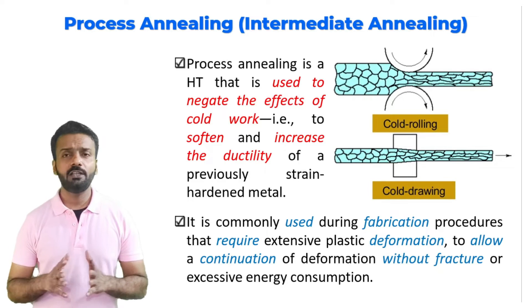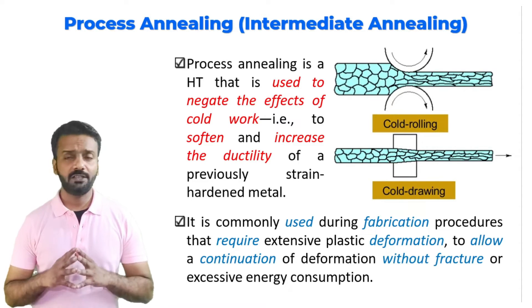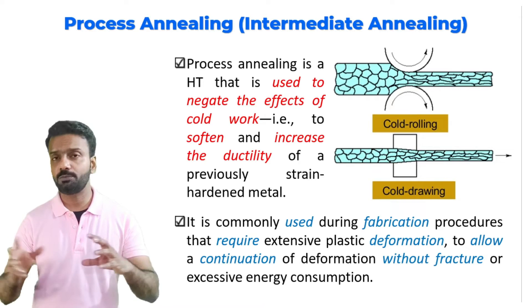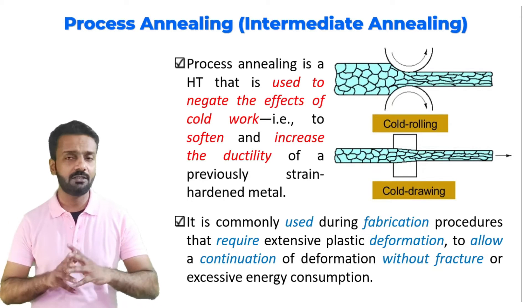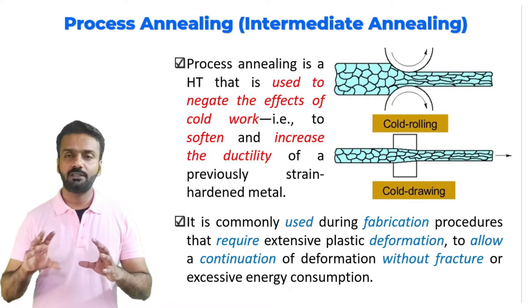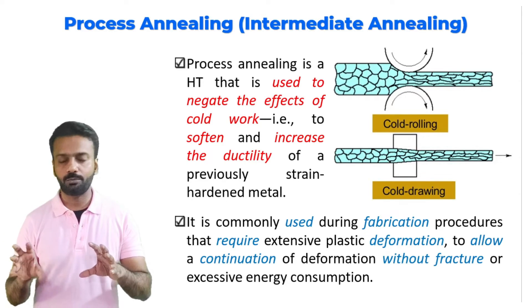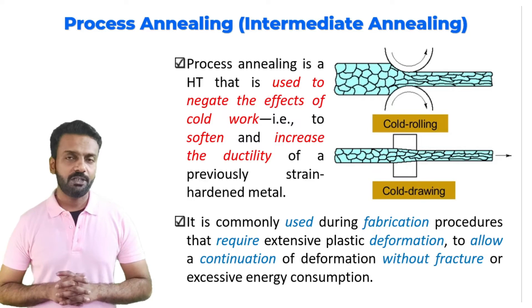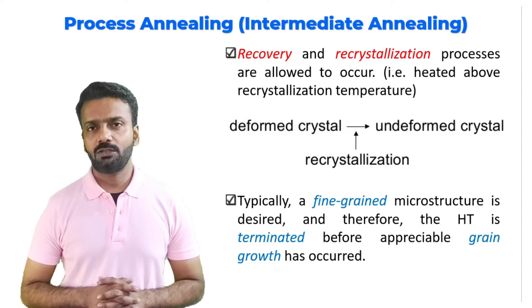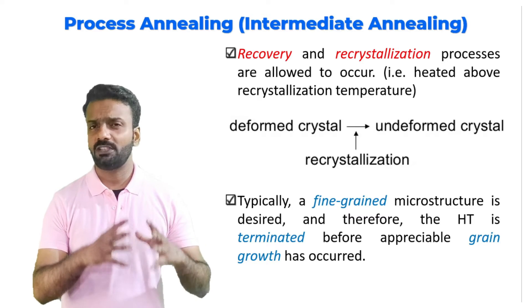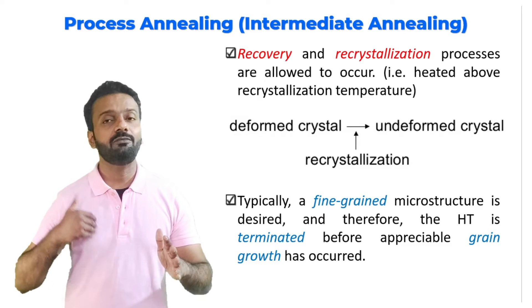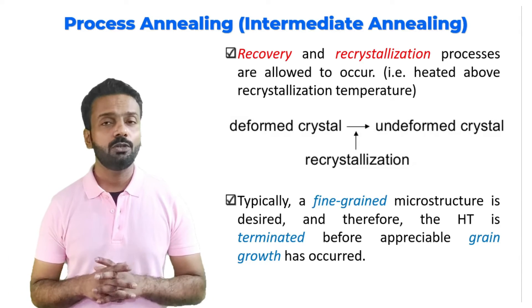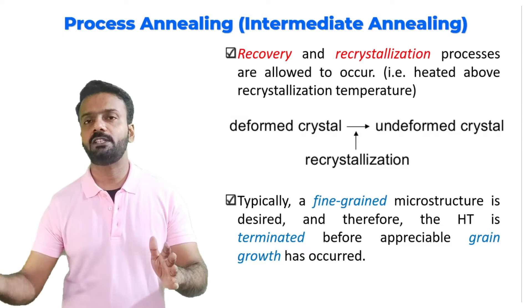Mainly during operations like rolling and forging, which reduce the size of the material, further deformation or rolling into smaller sizes eventually becomes not possible. So in the middle of that rolling operation we can do a heat treatment so that the grains become softer and further rolling is possible. In process annealing we go up to the recrystallization stage to get new fine crystals, and then the material is deformed again.